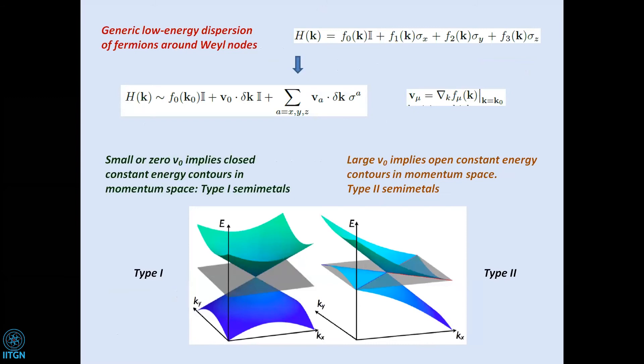Q: What is the difference between a topological insulator and a Weyl semimetal? A: In topological insulators, the band crossings in the 3D bulk are deep inside far from the Fermi surface — they are insulating materials and the gapless states appear only at the surface. For Weyl semimetals, they are 3D semimetals where the band crossings occur at the Fermi energy and involve all three components of the spin.